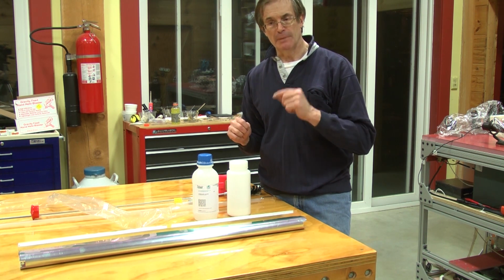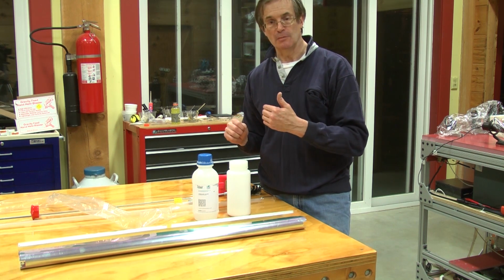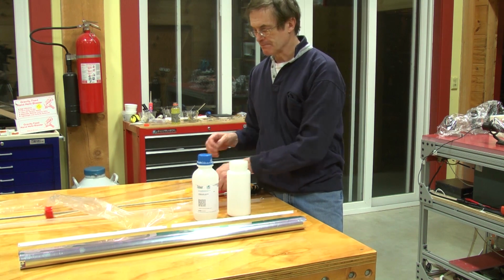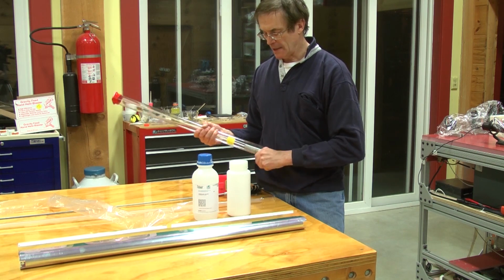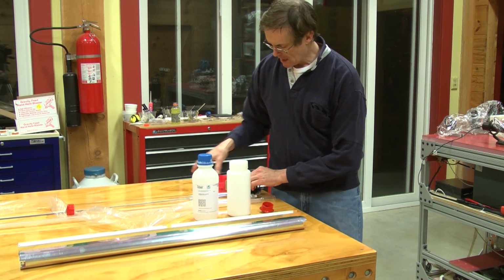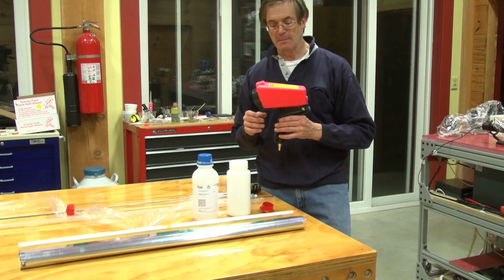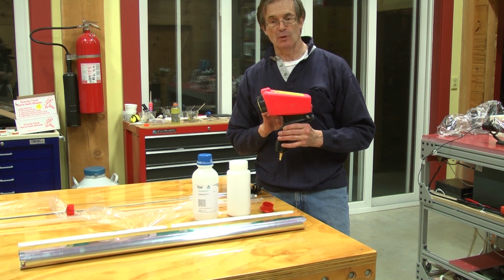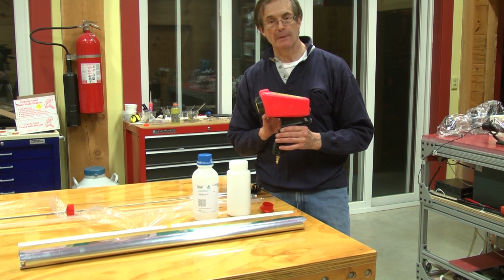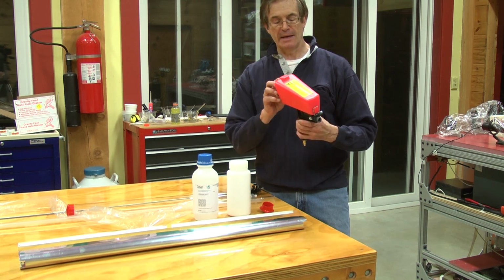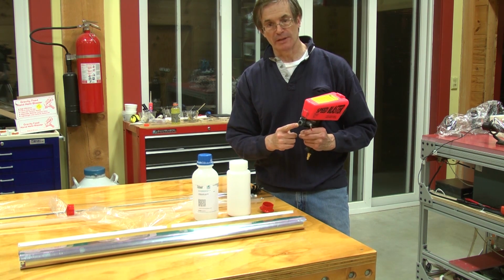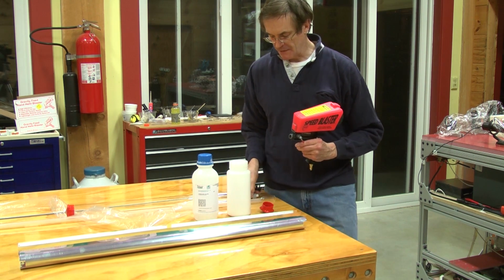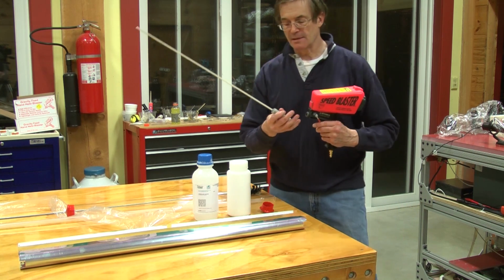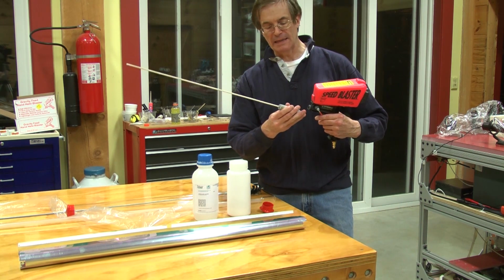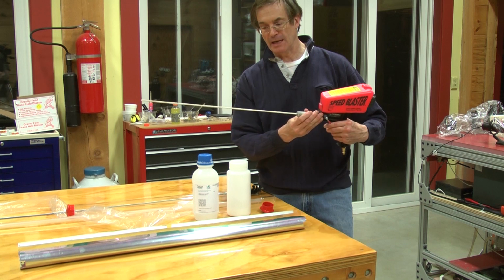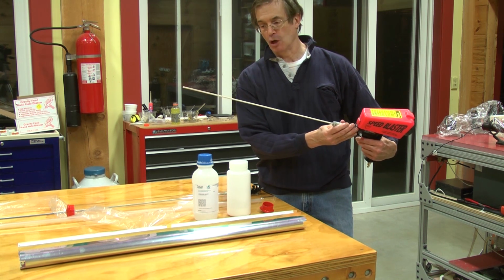But it provides a surface that's not very coarse, and it's not that diffusing. And so I found that I got a better result by using, again, mechanical means, but I did it in a little different way. What I did is I took a commercial sandblaster, first time use, so it wasn't dirty, and it's gravity fed, and I fill it with 120 grit silicon carbide abrasive material. And then I take the normal nozzle that goes on the front of this, and I modified it by placing this alumina or ceramic rod in the nozzle, so that when I place this in here, I have sort of a long gun with a long tip.